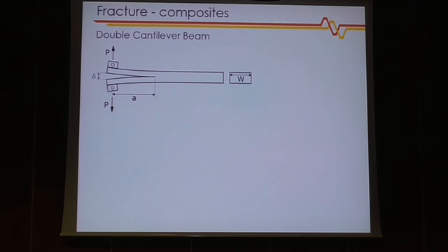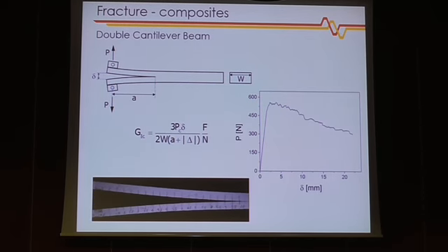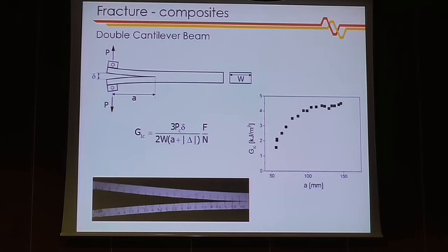For what concerns the composite materials, we investigated the fracture with the double cantilever beam testing configuration, from which, knowing the load, the displacement, and the crack length, we were able to measure the fracture toughness with the compliance calibration, which shows the value of fracture toughness as the steady state value of the curve, where the crack propagation speed was measured directly from the video recordings.